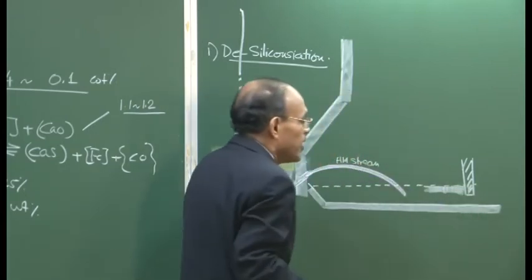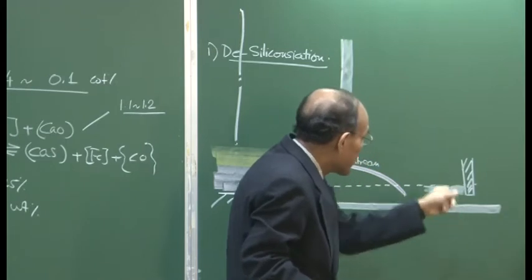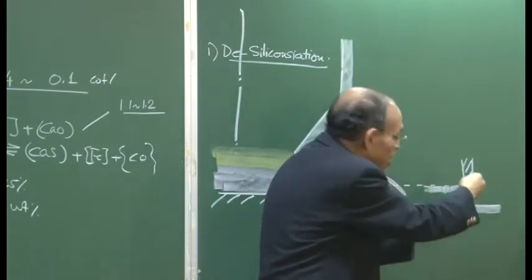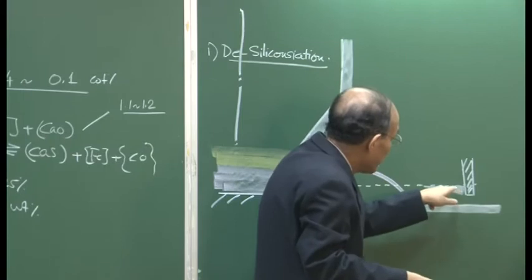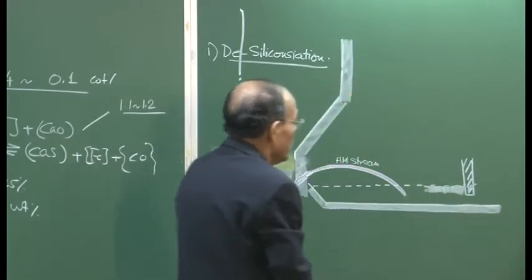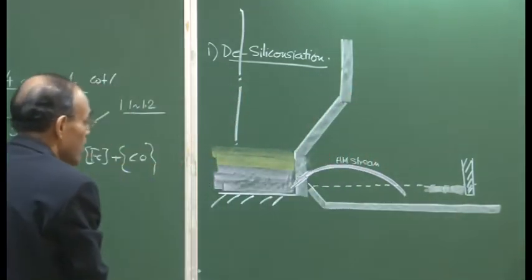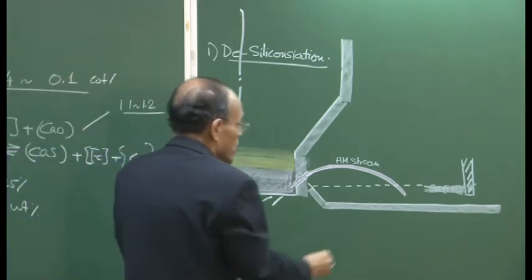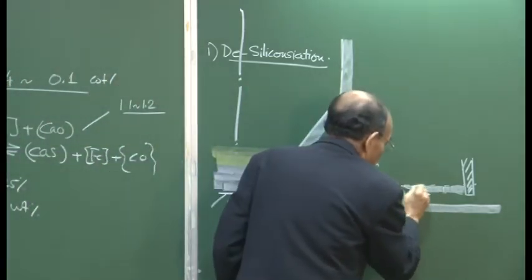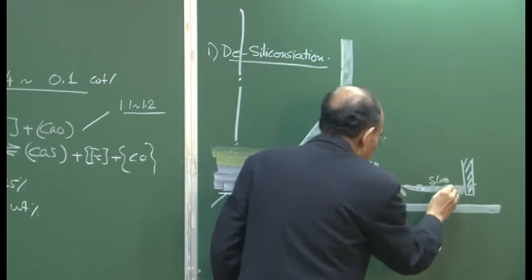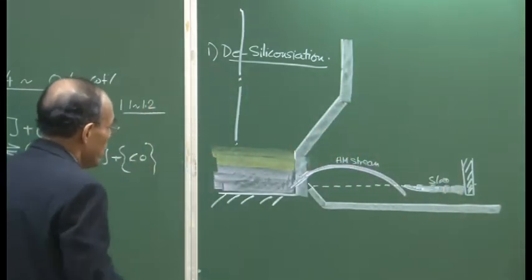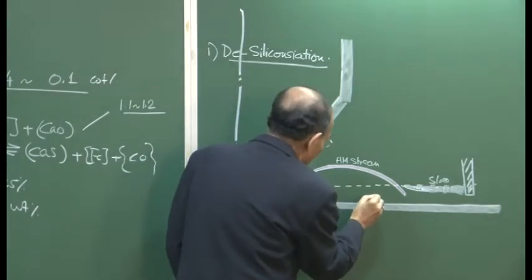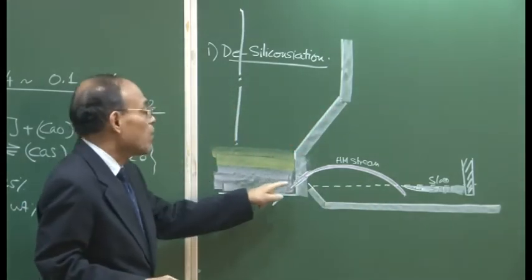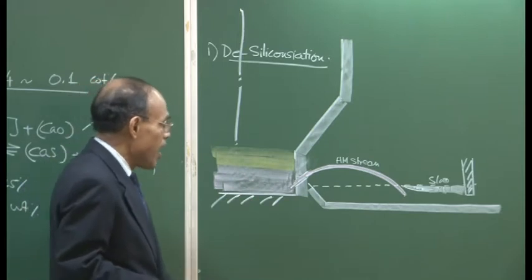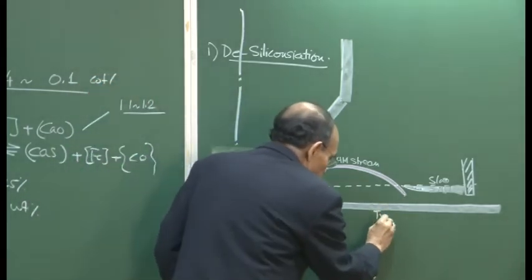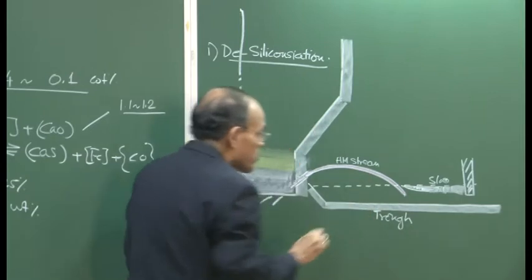And here there is a perpendicular direction, the slag can travel perpendicularly, there is another duct here, which will take this overflow. The metal will not go there, but the slag will go there. Okay? So this is how the slag is being generated. And when you trap the molten metal, this is called the tapping operation, tapping of the blast furnace. It is done periodically, and this is the trough, which is called the blast furnace trough.